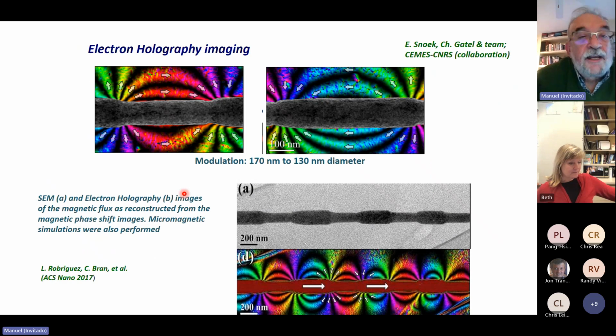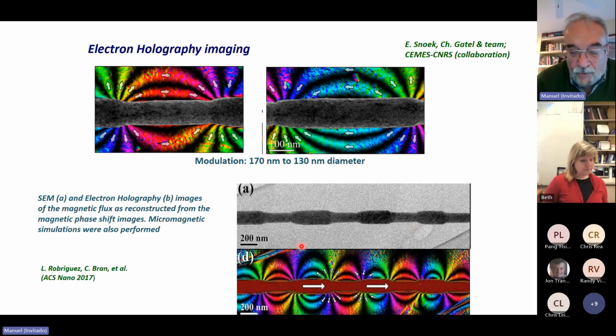So this is an electron holography image of a modulated nanowire. You see this is the nanowire, the small segment with a small diameter, and you see these colorful lines with arrows. What we are seeing here is the stray fields, the induction field, the magnetic field outside the nanowire. So we can see here that in the transition region between two different diameters, we have some accumulation of magnetic charges, positive and negative magnetic charges. At the bottom, we have a larger image of a number of different modulations in the diameter.